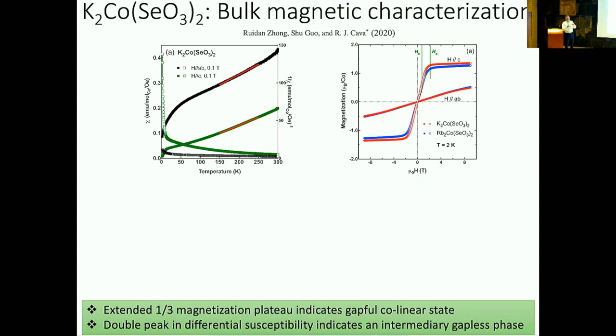Then we also apply a very large magnetic field. We go all the way up to 8 Tesla. We apply it along the C-axis, and we get this kind of saturation of the magnetization at a fairly low magnetic field. That's a little bit of a surprise to us, that the energy scale is so small in order to achieve the saturation magnetization. So we were a bit curious as to whether this was the final story.